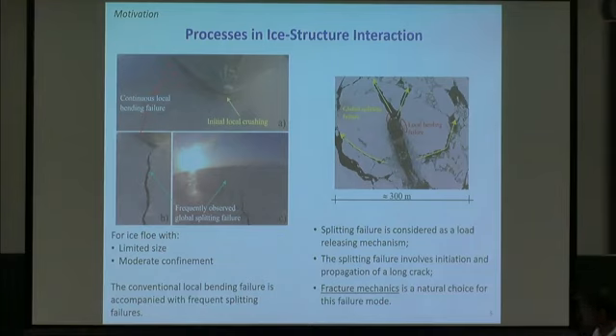So what can we then see? We see many different failure modes here, not just one. If you look at the hull here in the contact zone, you see that we have bending failure of the ice. We also have some crushing at the stem. In addition, there are splitting and circumferential cracking. All these things come more or less at the same time.